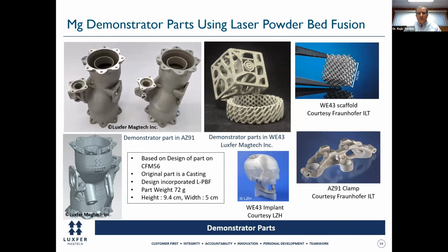In terms of demonstrator parts, this goes on to show what has been done in the last few years. You do see smaller demonstrator parts, as I've shown on the top right, the top bottom, bespoke implants which are being considered. On the left, we see pictures of a large demonstrator part that we built recently, where the original part is a casting. The design incorporated laser powder bed fusion process capabilities. The part weighs 72 grams, which is quite impressive. When you hold the part in your hand, it's amazing how light it is, with a height of 9.4 centimeters and a width of 5 centimeters. So there are these demonstrator parts being built, which goes on to show the confidence with magnesium additive, which resides with a few groups right now.